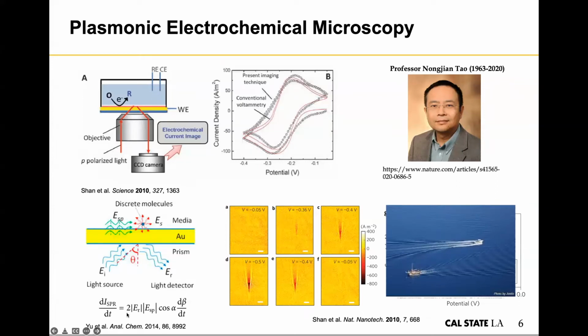And then if we want to be more mathematical, how do we describe the signal from individual nanoparticles? Here's an example, and you can see that the intensity of an individual particle is actually a combination of the partially reflected light and the plasmonic wave scattered by the nanoparticle, and it's affected by the scattering property of the nanoparticle, which is associated with the optical properties, for example, refractive index. So when you have an electrochemical reaction going on at the nanoparticle, causing the refractive index to increase or decrease, you will get an intensity change.